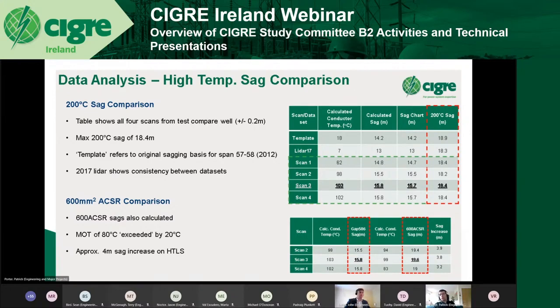The template SAG in the top row actually refers to the original sagging basis for span 57-58, the day the conductor was installed back in 2012. So that's the template SAG, or the theoretical SAG, that the designer would have assumed when carrying out the original design. And look, 18.9 versus 18.3, 18.4, anything within or close to half a meter shows very good correlation, particularly for a conductor that's been in service for almost 10 years. So that was certainly a positive note, and essentially validated the approach that we took and the overall behaviour.